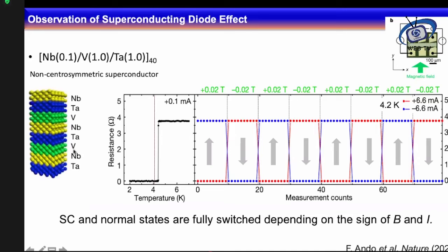What does it mean? It means that the inversion symmetry in this structure is broken, and with broken inversion symmetry we can have spin-orbit coupling. In this system, they measured the resistance versus temperature. It showed the zero resistance state, a very sharp superconducting transition closer to 4 Kelvin, so the system is in the superconducting state. Then they measured its resistance with different polarities of the current. For example, this red one is with the positive current, which is 6.6 milliamperes, and when they go to the negative current, which is the blue one, you can see you can switch between zero resistance and high resistance.